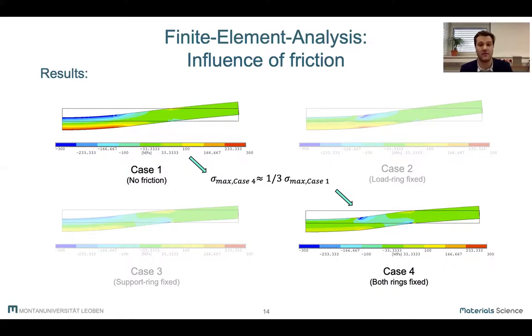And therefore we can assume that friction always decreases the maximum stress. Now if we test the specimen with friction, the maximum stress decreases and a higher load would be necessary for specimen failure. This means that an apparently higher strength should be measured, which sadly was the exact opposite of what we observed. So since friction could not explain the decrease in strength, we looked for some other explanations.